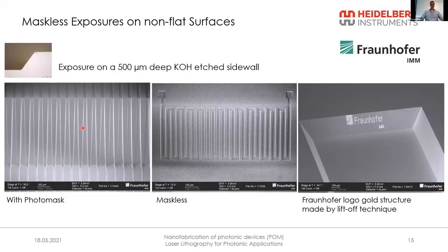And this is the first attempt they tried with a photomask. As you would expect, on the top surface, everything looks nice. But the further you go away from the photomask, the line width changes, and the pattern down here is not what you want it to be. With a direct write system without contact, they managed to write these very uniform structures on the sidewall, and they even exposed their logo and etched it in or created it in gold to show what they can do.